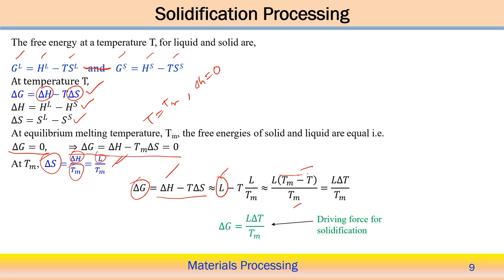Here Tm minus T is delta T, so delta T equals Tm minus T is the degree of undercooling, and Tm is the melting point temperature. So the driving force for the solidification, delta G, equals L delta T by Tm. A higher degree of undercooling means more driving force to start the nucleation process in solidification. So here we can approximately calculate the driving force for the solidification to occur.